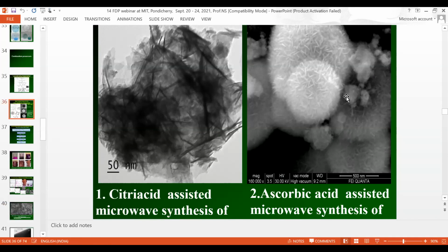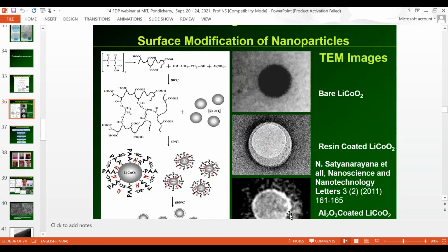Here, lithium cobalt oxide, when it is in direct contact with the liquid electrolyte, the liquid electrolyte will react with it over time. The electrolyte and electrode interface will change, so battery properties decrease very fast. To avoid this, we did nano coatings of 2 to 3 nanometers. If you coat at 2 to 3 nanometers, it still allows the ions to move, but your electrolyte will not interact with the electrode material, because of this nano size coating of aluminum oxide.